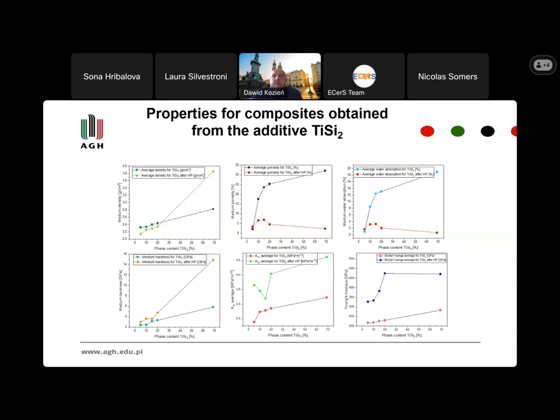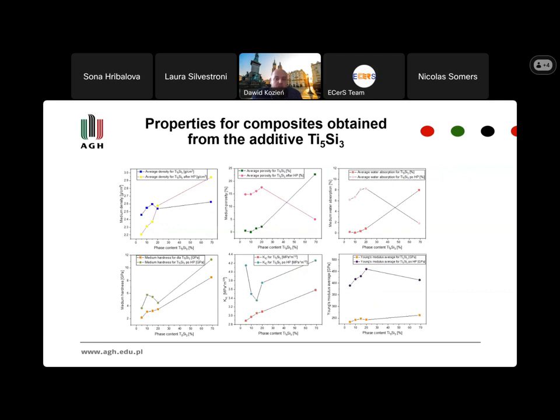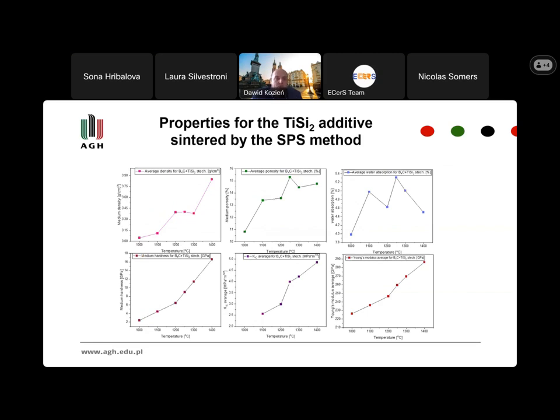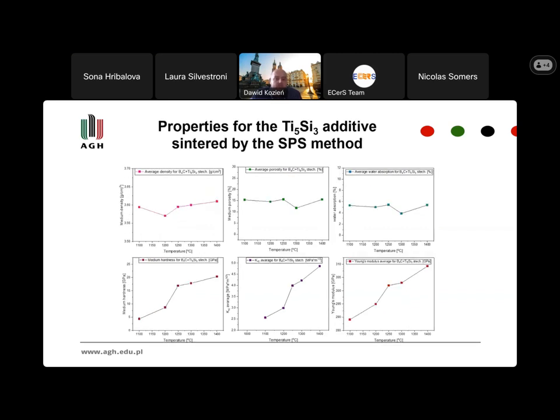Here we have some properties of the material obtained from different additives of intermetallic. We can see the results of physical and mechanical properties for the obtained composite, compared to the results for the given methods. The graph shows that for the additive in the form of titanium disilicide, we have high results for density as well as hardness and Young's modulus. So it's quite good. We have better densification and a better composite after the sintering. The same situation holds for the other intermetallic additives, but it could be more problematic to compare these two intermetallics. It's better to add titanium disilicide, with the lowest synthesis temperature.